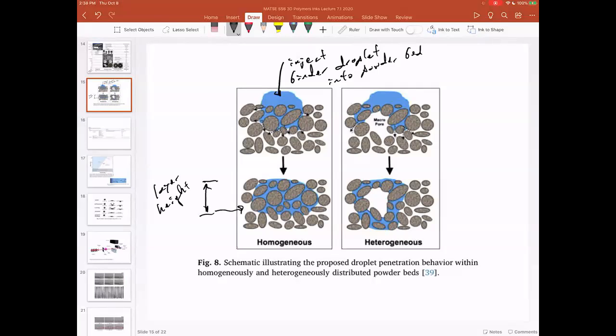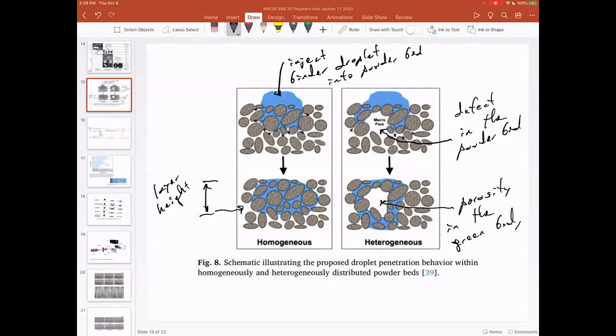And so any defects in the powder bed, so this is a pore or a defect in the powder bed, will cause porosity in the green body. And that's bad, especially if you're not going to do post-infiltration. Porosity in your green body will lead to sintering defects, which will lead to weak parts. And so getting a really nice homogeneous powder bed is important.